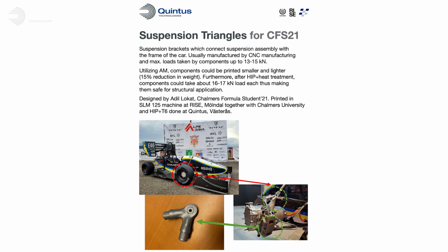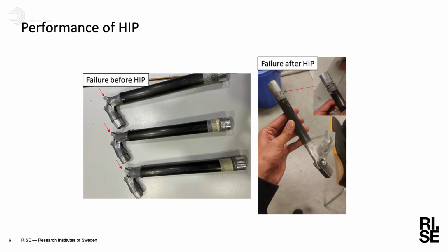So the students there have designed the part using topology optimization and such to fit into the car and be as lightweight as possible. The part was then printed at our facility and then tested, and they could see that it broke in one of the areas, as you can see in the image. But then after introducing HIP, they could see that when doing the same testing condition, the part never broke. It was actually the glue fixating the mechanism when they were pulling the part that broke before the part, so they could increase the performance of the part a lot with introducing the HIP to the part.